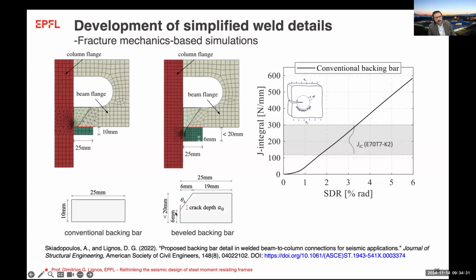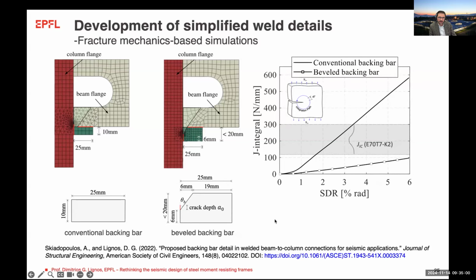Now, we worked with an alternative geometry of a backing bar where we introduce a bevel, and you see here that you bevel the backing bar at a certain angle. Then instead of starting the weld right on the beam flange, you start the weld outside of the flange, right where the bevel starts. If you repeat the simulations by introducing the bevel here, you see that fracture potential could still be the case, but at drifts that are much larger than what we anticipate in a maximum considered event.